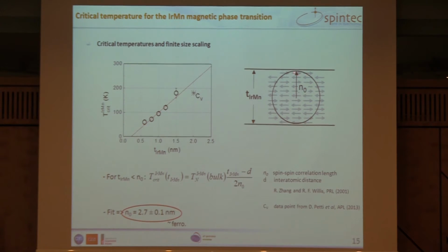So the model simply states that the critical temperature somehow should be related to the amount of interspin interactions. So whenever you remove one layer here, you remove some interspin interactions, and you should reduce your critical temperature. And this model can fit our data quite well. And from this, it's possible to extract a parameter that I think doesn't mean much. It's a kind of effective spin-spin correlation length. Well, we can extract these kinds of parameters. There were talks about critical exponents some days ago. This model is a model in the mean field approximation, so lambda equal to 1, I think.